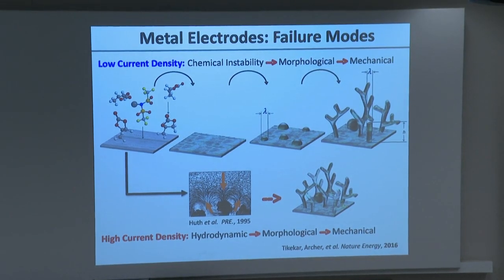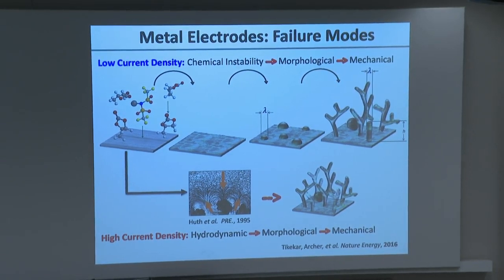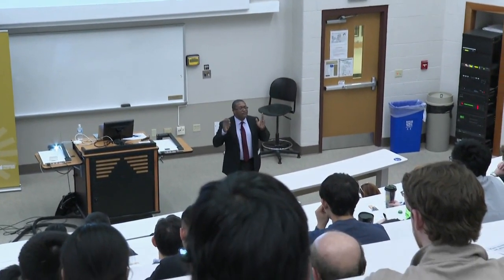The second pathway is actually somewhat more interesting, and one that I will start with in terms of proposing solutions. Basically, any electrolyte that contains cations and anions driven at a current above a certain special value called the diffusion limit, which is sort of like the speed limit at which ions can move in a liquid electrolyte, develops a hydrodynamic instability that looks like turbulence, the fluid mechanical turbulence.